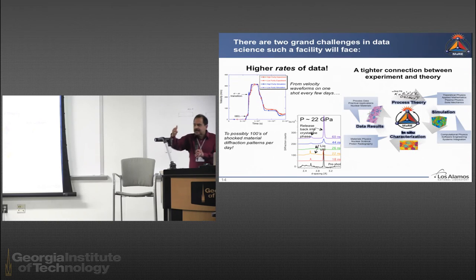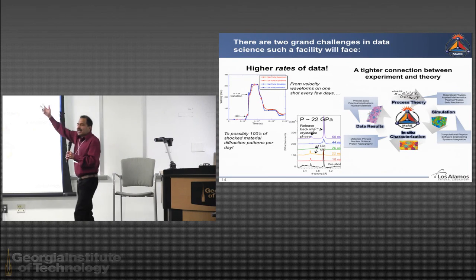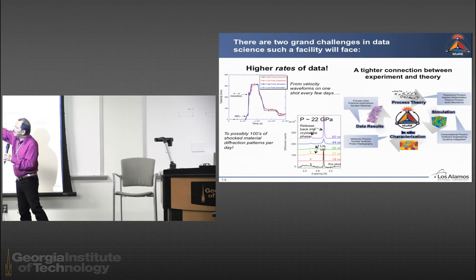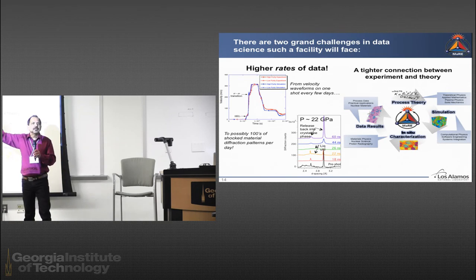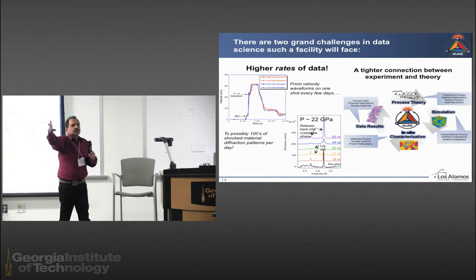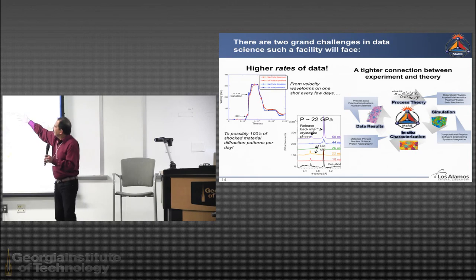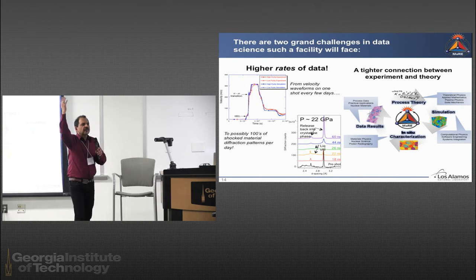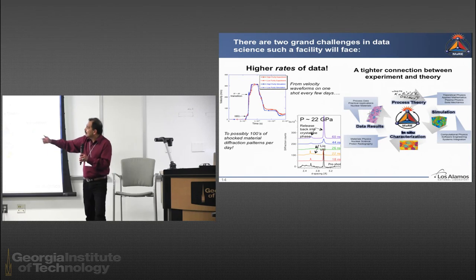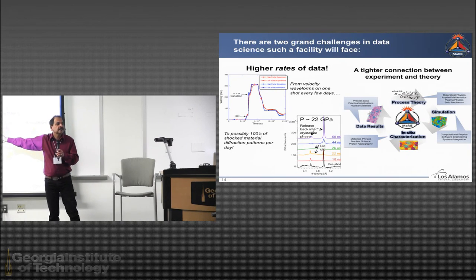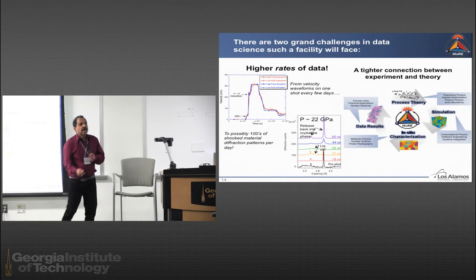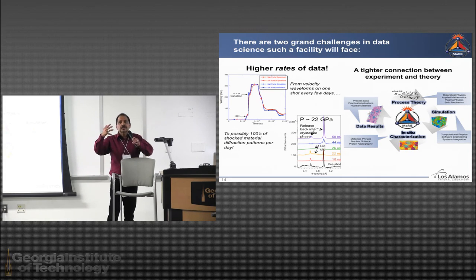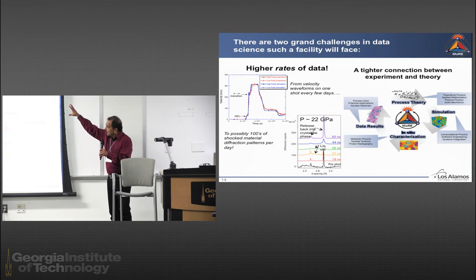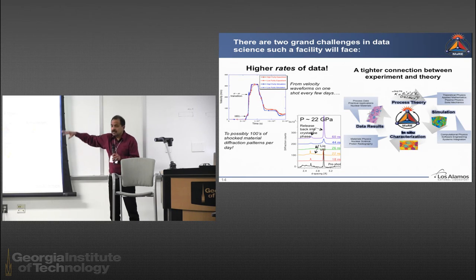So in terms of data, whereas now we basically get one VISAR plot. So that's a velocity profile when you do a shock experiment, okay? You basically get one every few days. With MaRIE, we will be able to get hundreds of these, okay? And that's where the large data starts to enter in this game. So that's where we're heading towards. And of course, the integration, this co-design loop is very, very critical.